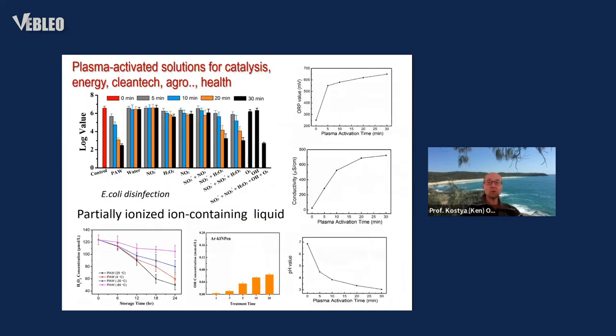And now we can process liquids using plasma. When we process liquids using plasma, we substantially and fundamentally modify the chemistry of the liquids. Essentially, we electrify the liquids by injecting electrons and ions into the liquid, and we make them more electrically conductive. We make them a lot more reactive, increasing the oxidative capacity of these plasma-activated solutions.